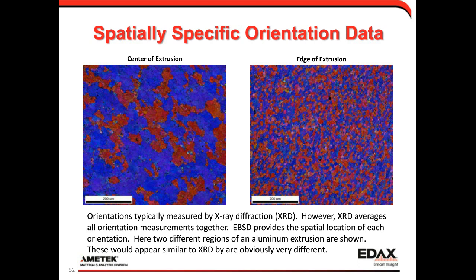The area fractions of both are actually pretty similar as well, but we can see the spatial distribution is quite different. There are much larger clusters of a given orientation towards the center than there are towards the edge. And so if you were to measure this area with XRD, you wouldn't be able to tell there's a difference between these. And if you look at grain size and texture on this, you don't see a difference. It's only by seeing the spatial distributions that these become more obvious.